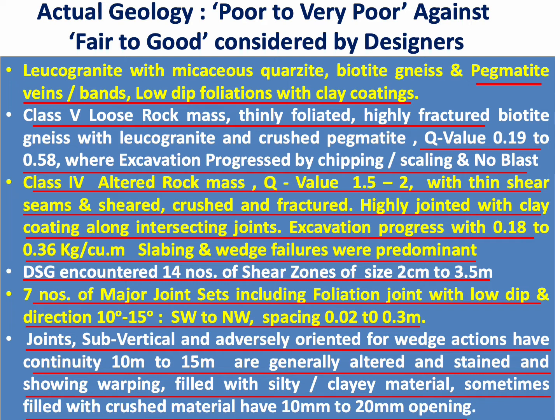Amongst these 7 numbers of major joints, besides the very flat foliation, there were joints which were subvertical and adversely oriented for wedge action and had continuity of 10 meters to 15 meter and are generally altered and stained and showing warping and filled with silty clay material, sometimes filled with crushed materials, and have 10 millimeter to 20 millimeter openings also. So this is the geology of the problematic reach.